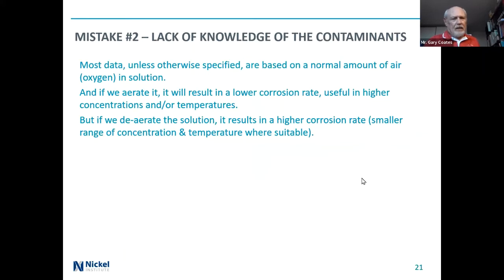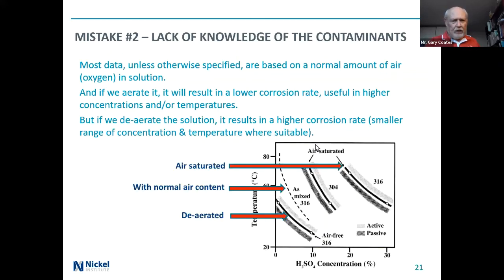Most of the data that is generated is based on just a normal amount of air, oxygen in the solution. And if we aerate it, it will result in a lower corrosion rate, useful at higher concentrations or temperatures, just like that, those ferrous and ferric ions. And if we de-aerate it, take out all the oxygen there, you get a smaller range. So here is the curve.